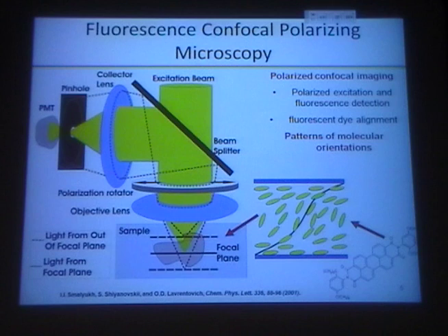And just like conventional confocal microscopy techniques, it utilizes dyes that are doped into the liquid crystal in small quantities, except that those dyes are anisotropic molecules, very similar to the liquid crystal molecules themselves, and also the imaging is done using polarized, typically linearly polarized, excitation light.